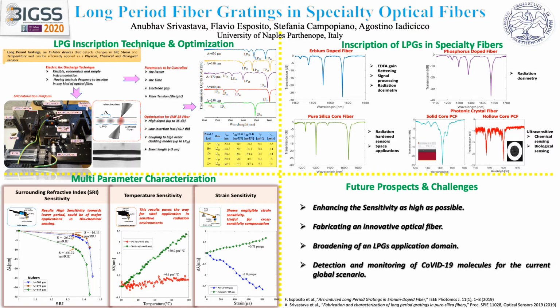So let's come to the long period grating inscription technique and optimization. What actually are long period gratings? They are in-fiber devices which consist of periodic longitudinal perturbations of refractive index and/or the fiber geometry along the optical fiber that promotes the coupling between the fundamental guided core mode and co-propagating discrete cladding modes at some resonance wavelengths, due to which the transmission spectrum of long period gratings is characterized by discrete attenuation bands. These bands are positioned at resonance wavelengths satisfying the phase matching condition.